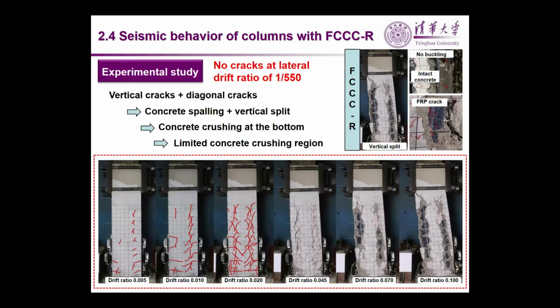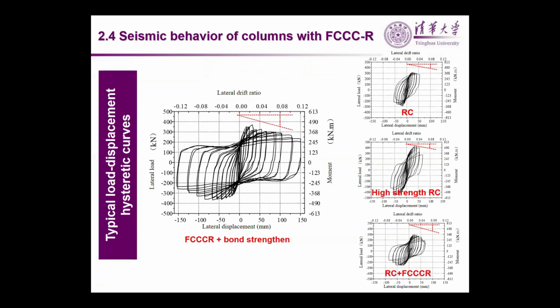But this failure mode will only influence the column's behavior at a relatively large lateral drift ratio, but has little influence around the peak point. And besides the failure mode, the bearing capacity and hysteretic performance of the columns were obtained and compared. By adopting some bond strengthening configuration between the FRP tube and the concrete cover, such as applying a quite thin FRP jacket to the columns, the seismic performance of the column can be enhanced significantly and show quite excellent hysteretic performance.